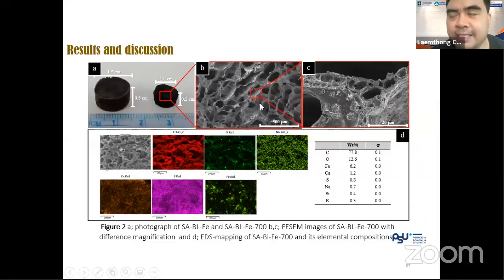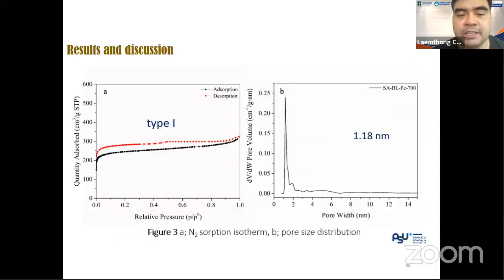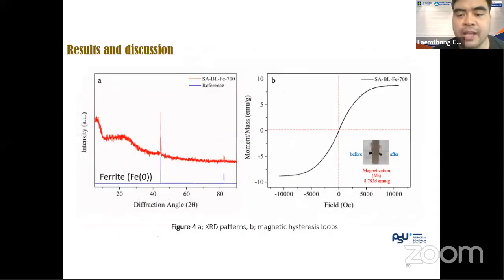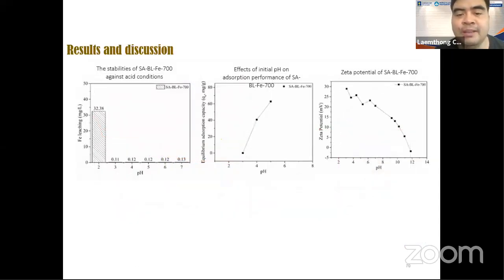It's not really light like a carbon nanotube or graphene sponge, but comparing the price, this is much cheaper. I would say 100 times cheaper than the carbon nanotube sponge. Okay, and we determined it, and so we use it to adsorb. If you notice the picture here, we also still have the magnetic property. So not only do you have the granular shape, but you can also attract it by using a magnet. So this is quite cool in this case.